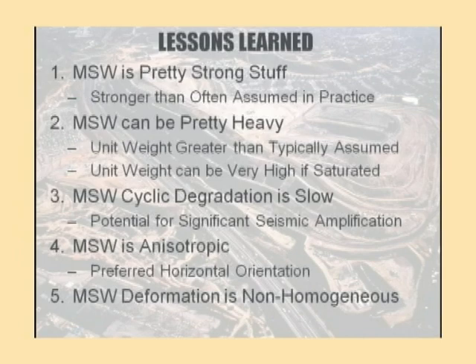Also that municipal solid waste can be pretty heavy, that the unit weight is greater than typically assumed. And I didn't mention this, but in the saturated zones, we were getting unit weights on the order of 130 pounds per cubic foot. And that's actually gotten more relevant today as people move towards bioreactor landfills, where they're introducing liquids into the landfill, and I review the designs for these landfills, and they're still using 85 pounds per cubic foot as the unit weight. No, that's not what it's going to be if that waste is saturated.